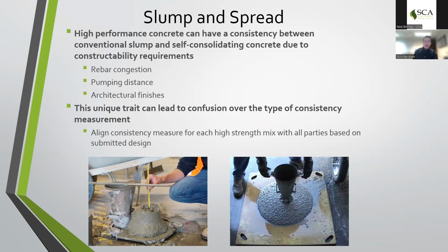If you're doing architectural finishes or there's major concerns on rebar congestion, specifying the use for a given pour of a 26-inch spread can really help both the producer, the quality control technician at that yard especially, but then the tester on site and the contractor on site order and receive a product that they actually want to work with. And so figuring out how, in the language of ordering, consistency can be a huge benefit to all parties involved.